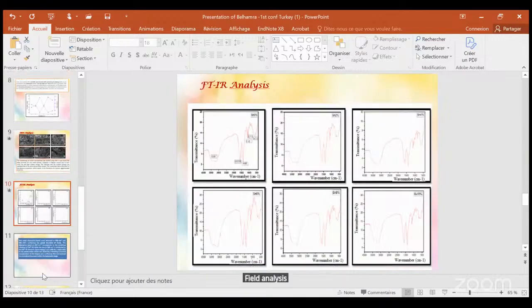After analysis, we can see in this figure two weak absorption bands recorded at 690 and 596 cm-1, confirming the spinel structure of Co3O4. The absorption band at 690 corresponds to the stretching vibration of Co2+ to oxygen, while the one at 596 is attributed to the Co3+ to oxygen vibration.